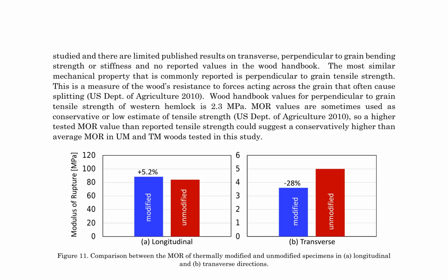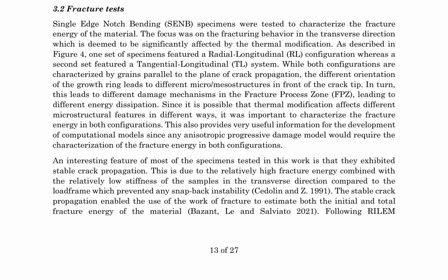Fracture tests were conducted using single-edge notch bending, SENB, specimens to characterize the fracture energy of the material, particularly in the transverse direction. Two configurations were tested: radial-longitudinal, RL, and tangential-longitudinal, TL, as these orientations can lead to different mesostructures and damage mechanisms in the fracture process zone, FPZ, resulting in varying energy dissipation. The thermal modification may affect different microstructural features differently, making it crucial to analyze the fracture energy in both configurations.